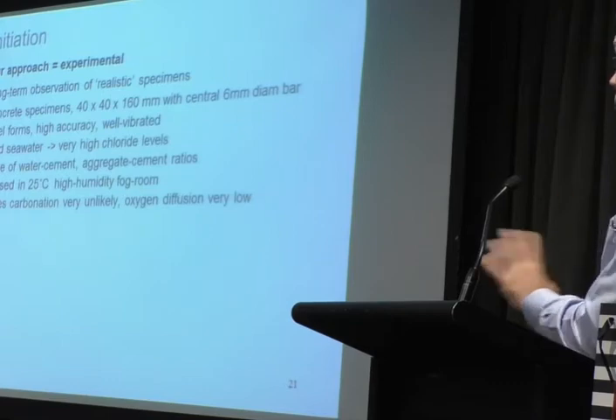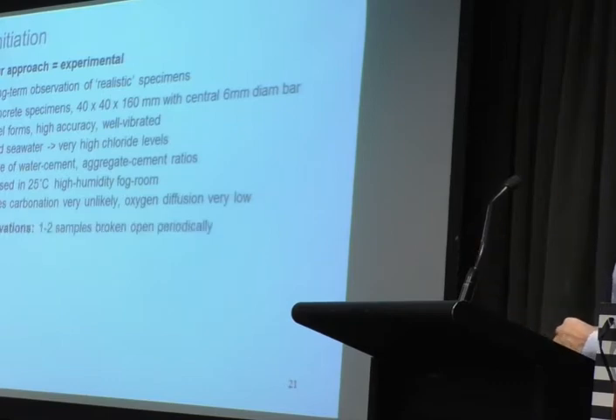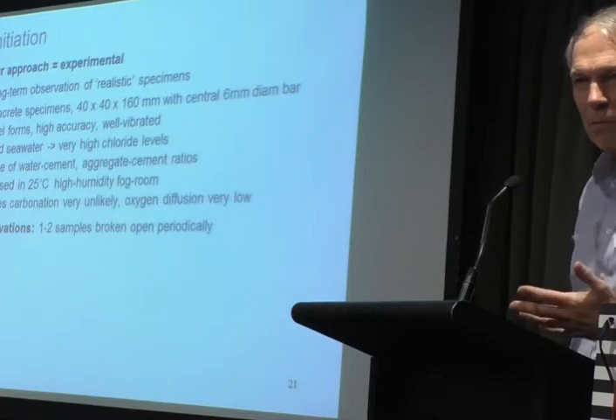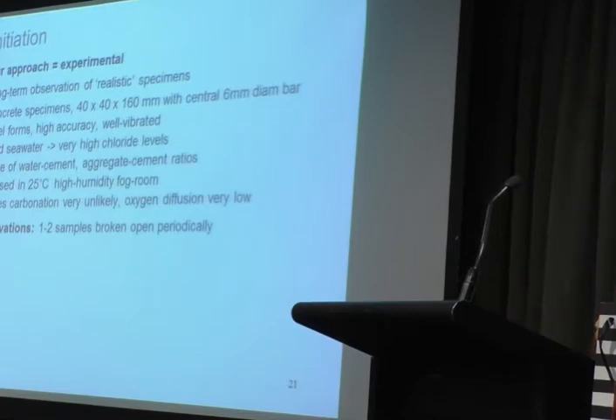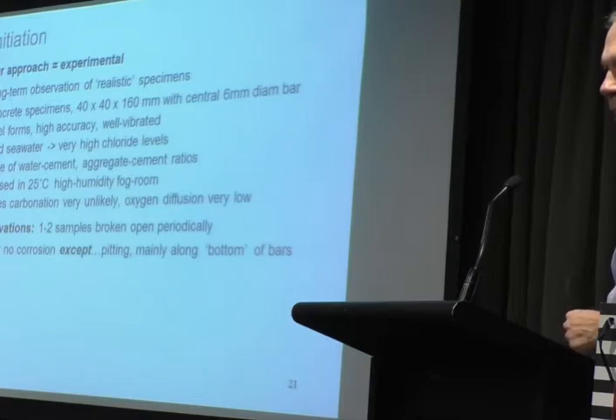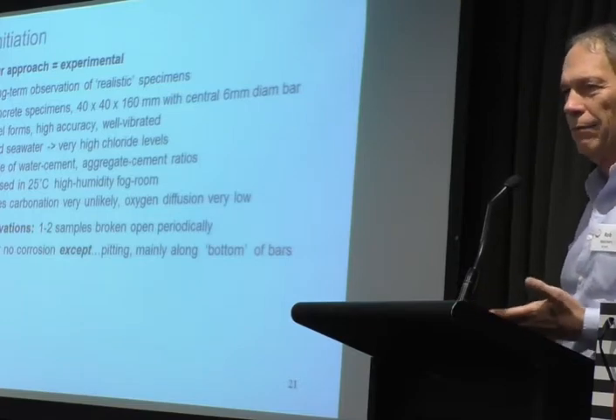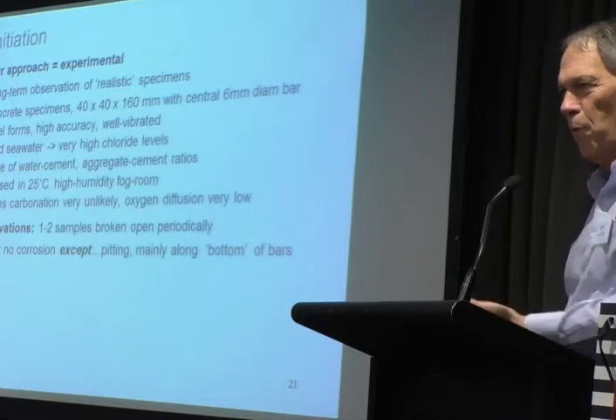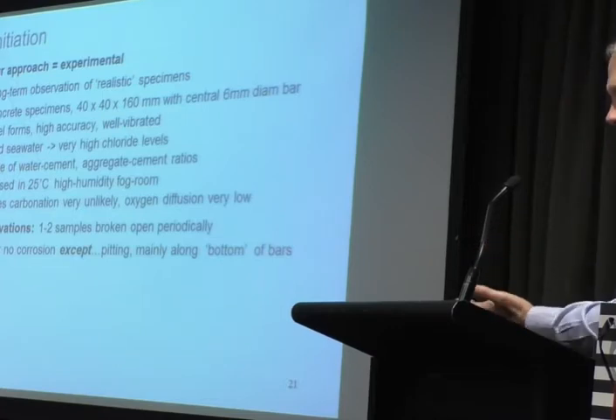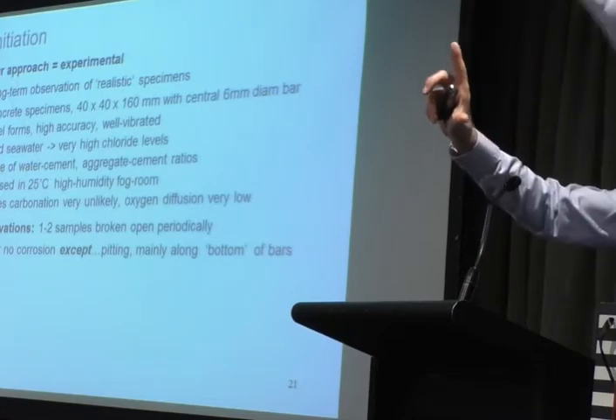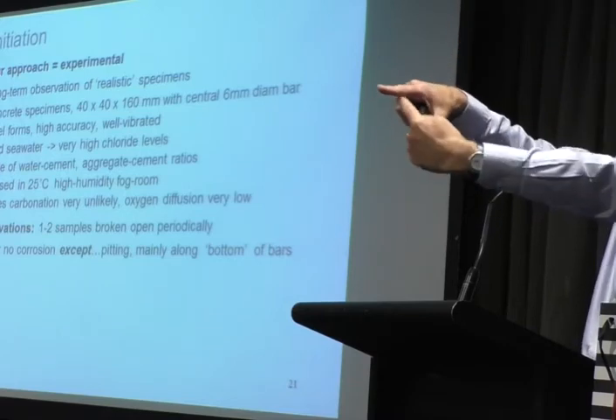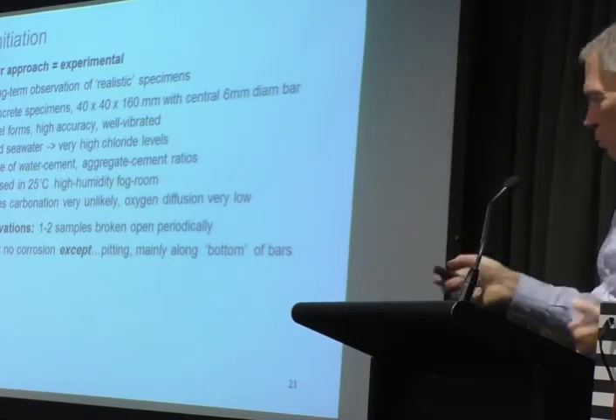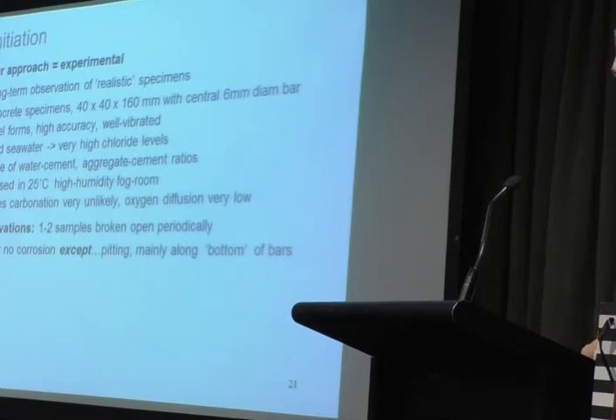And that actually means that we can rule out carbonation as an issue. And then every year initially we broke open 2 samples to have a look, and we saw nothing for these things. Except after a little while we saw pitting along one side of the bar, if I can call it a side. And it was the bottom of the bar, away from the casting direction. So we had them like this, we cast on top, the bar was through here, corrosion was on the bottom. And when we looked more closely, I'll show you some pictures.